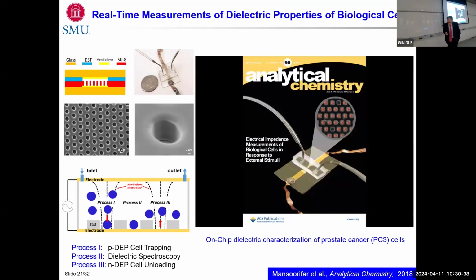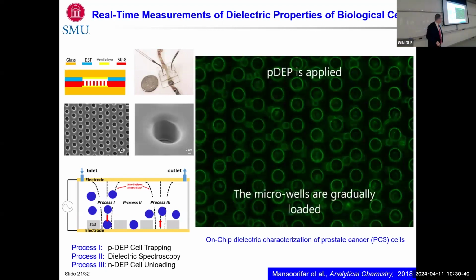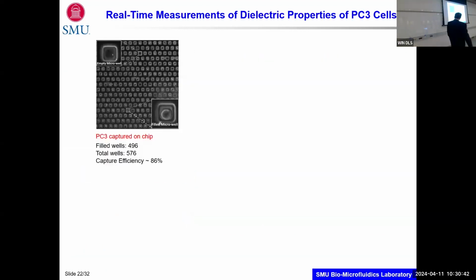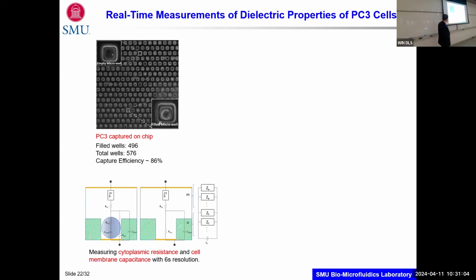So it made the cover of Analytical Chemistry 2018. So how do you analyze something like that? Fortunately, we can take a picture and we can see that with a total of 576 wells, 86% of them were filled, which is good. So with one shot, we are measuring approximately 400 to 500 wells and cells.